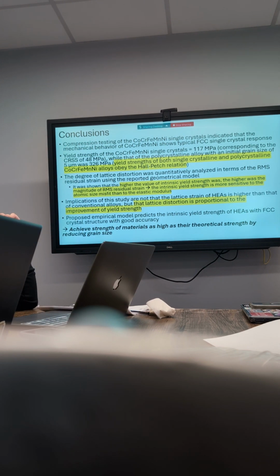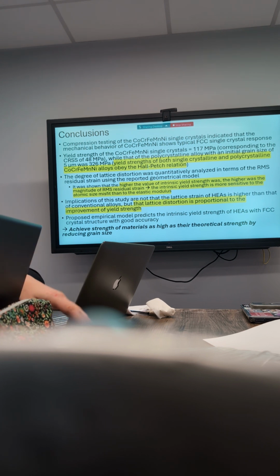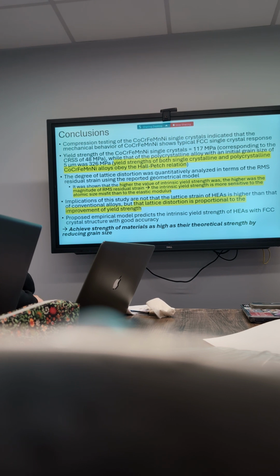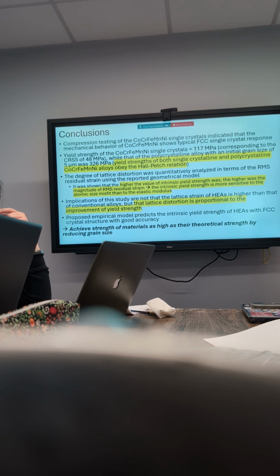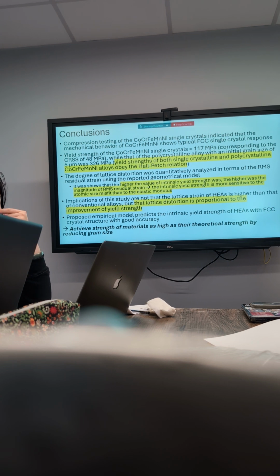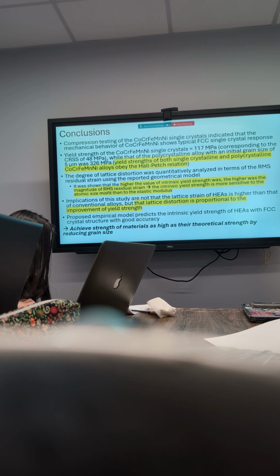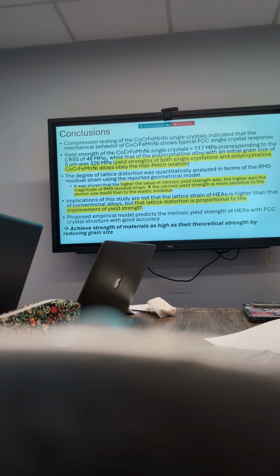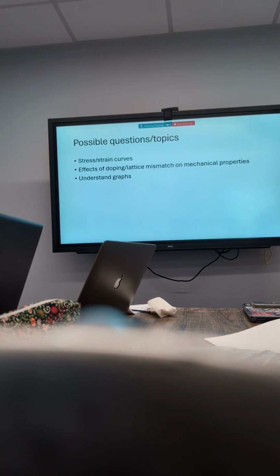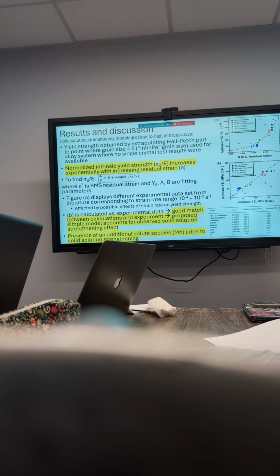The main focus here, or one of the main takeaways I took from their conclusion, was that the implication of this study is not that the lattice strain of HEAs is higher than that of conventional alloys, but that lattice distortion is proportional to the improvement of yield strength, which I thought was important because the first incorrect implication I definitely would have assumed from this, but they want to say that lattice distortion is proportional to improvement of yield strength. So they're able to achieve the strength of materials as high as their theoretical strength by reducing grain size. That is their main focus, is what they touch on. This was a very weird paper.